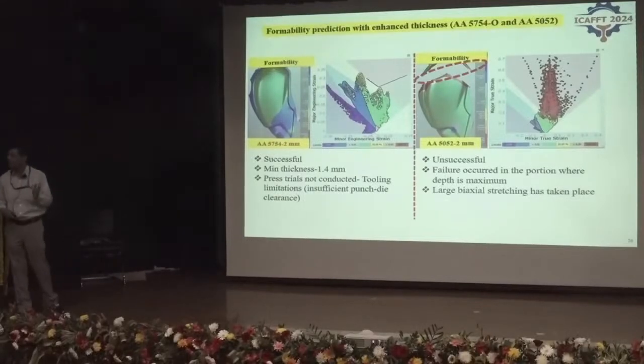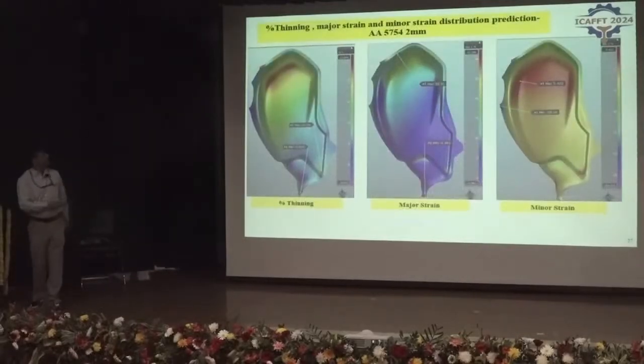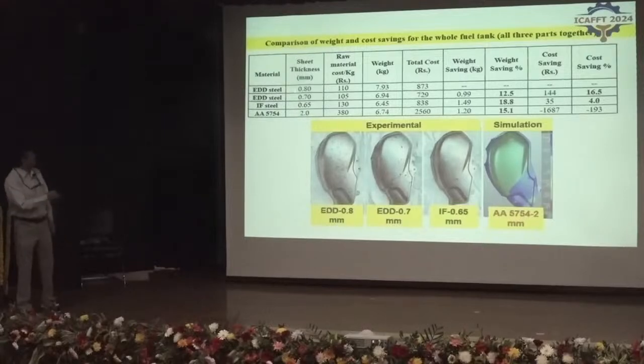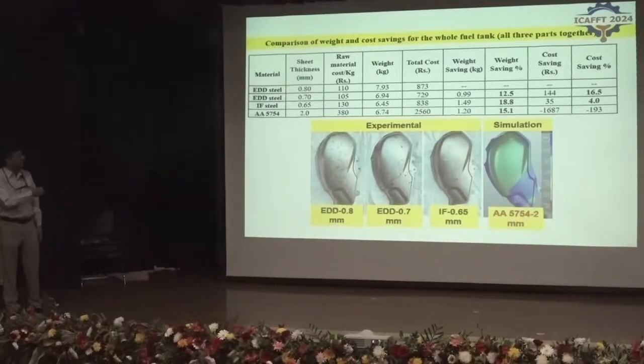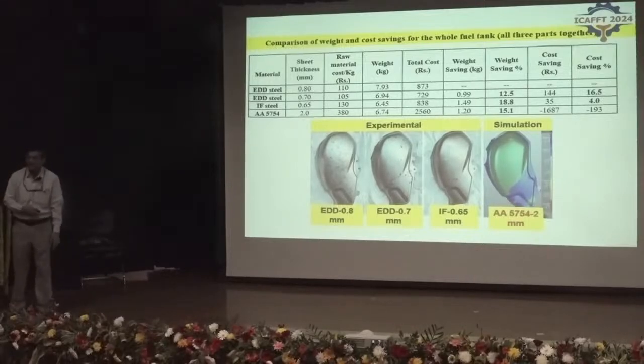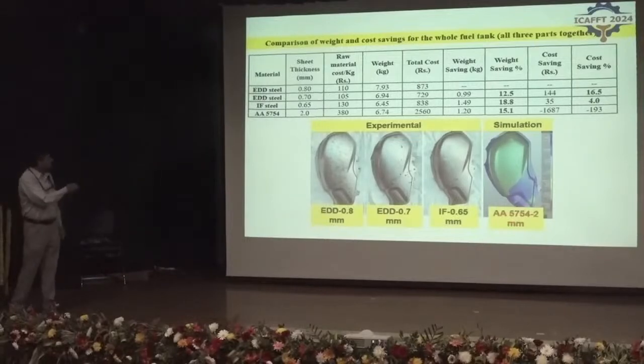The actual press trials could not be done with aluminum alloys with 2 mm, because the current tooling in the industry was made for 1 mm sheet. The tolerances and the punch and die design clearances and everything were made for 1 mm. So therefore the press trials were not done. So just to give a comparison now, EDD steel 0.8, if we can reduce it to 0.7, it gives us about 12.5% weight saving for this one particular component alone. And similarly, if we change the grade to IF, which has much better formability than EDD, we can even go down to 0.65, so that would give a weight saving of nearly 19%.